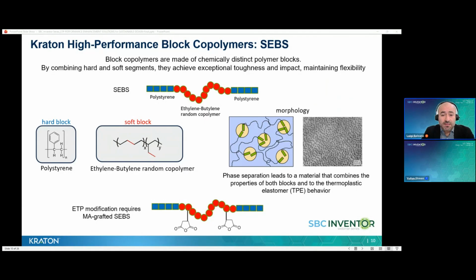The physical properties of this material are controlled by a nanometer scale phase separation. In fact, as often in block copolymers, the hard and the soft block, polystyrene and the ethylene-butylene random copolymer, are physically incompatible. They tend to phase separate on the nanometer scale and form a morphology where the polystyrene hard domains are dispersed in a soft elastomeric matrix. Phase separation leads to a material that combines the properties of both blocks, and it is the basis for the thermoplastic elastomer behavior.